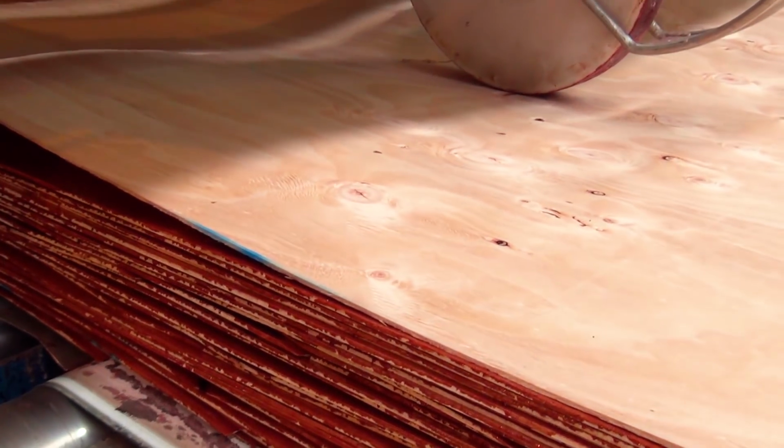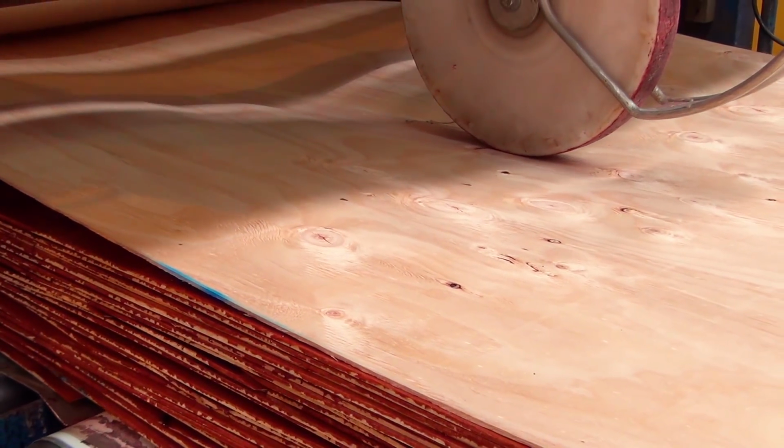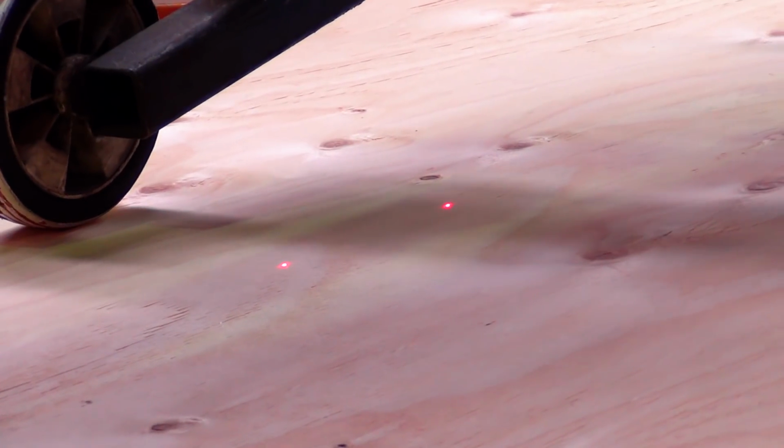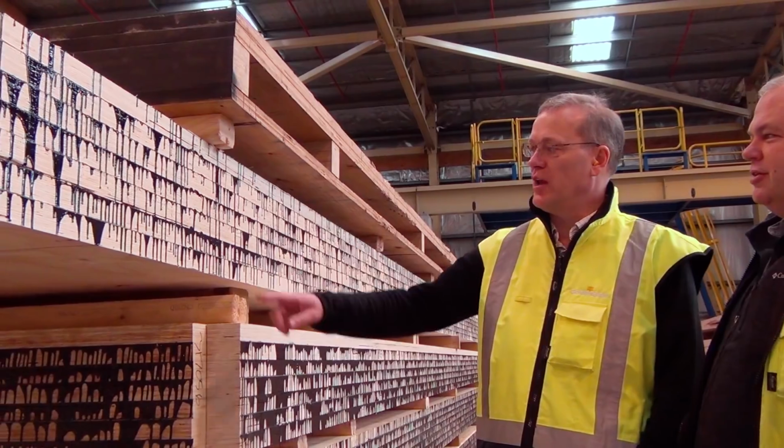While the LVL process itself is quite simple, the real-time measurements of the veneer and the processing have to be very sophisticated. We are able to identify and measure physically the property, strength, moisture and appearance through scanning cameras and other electronic sensors. So it allows us to make absolutely informed decisions about the specific properties of each individual veneer sheet, and later on we will combine individual veneer sheets into an overall product.